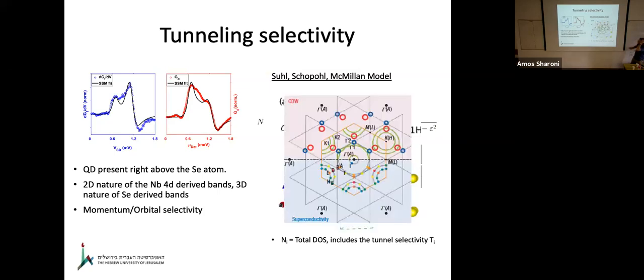Another possibility is that in momentum space, these are the selenium levels over here, and since tunneling through a dot tunnels into the low momentum states, there's a momentum selection rule that favors these states over these states, which are at high momentum. We actually don't know because we have only a single dot. A third possibility is there's some kind of an orbital order related to the structure of the orbital of the defect.